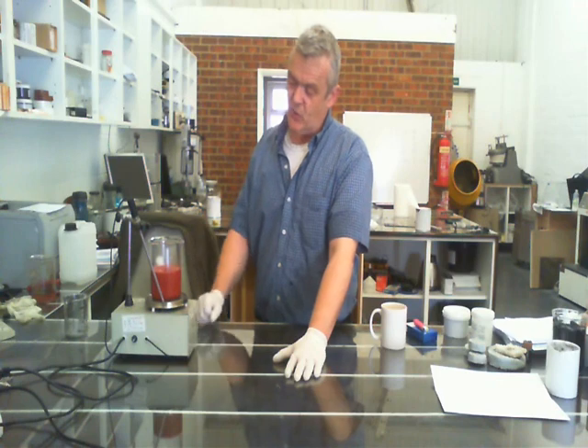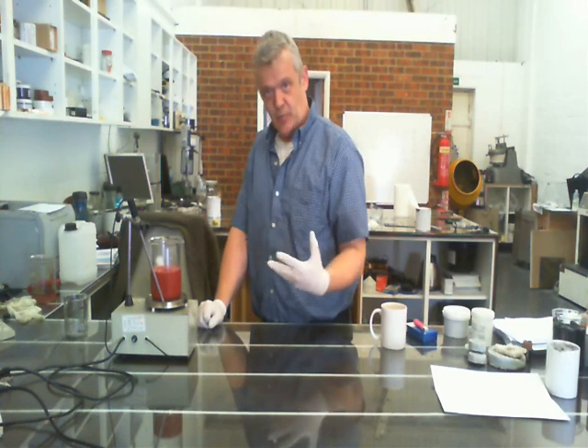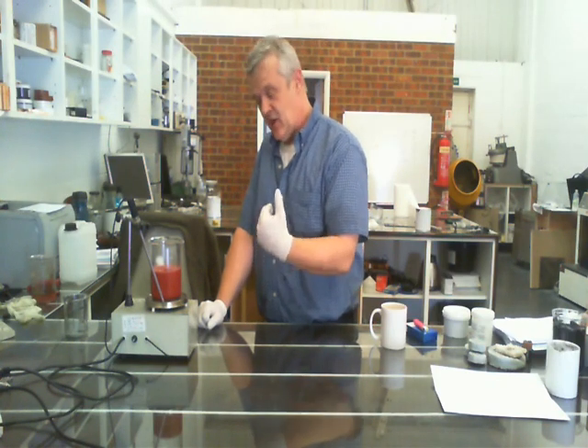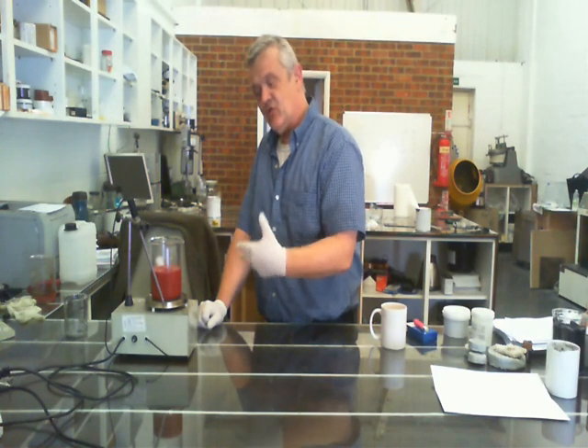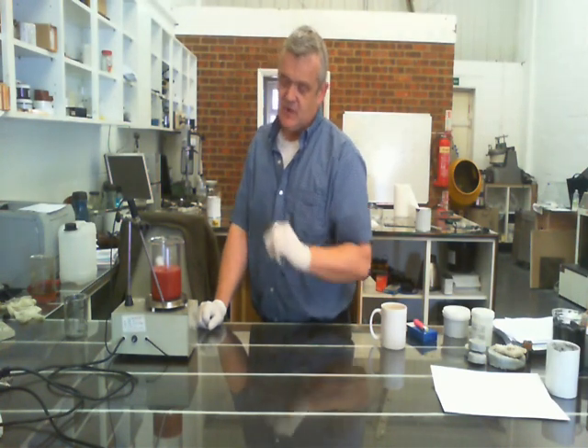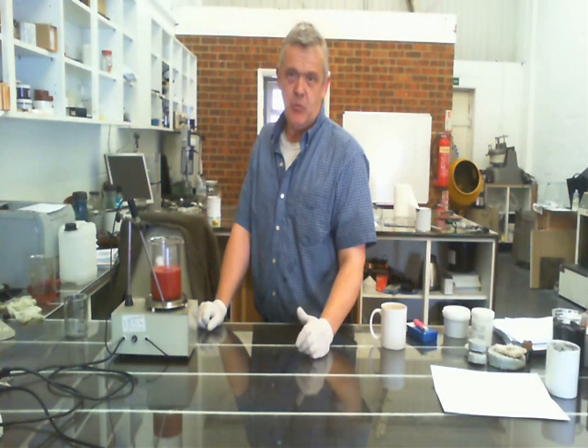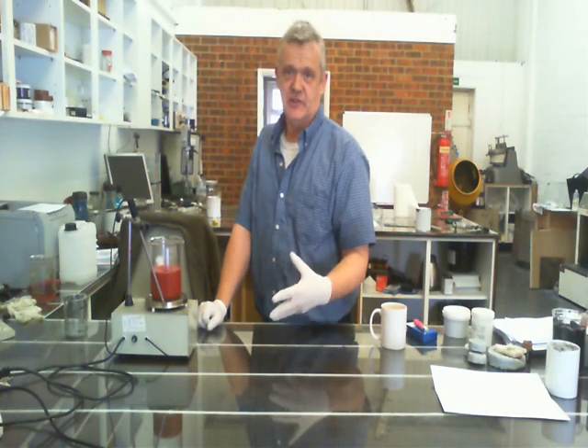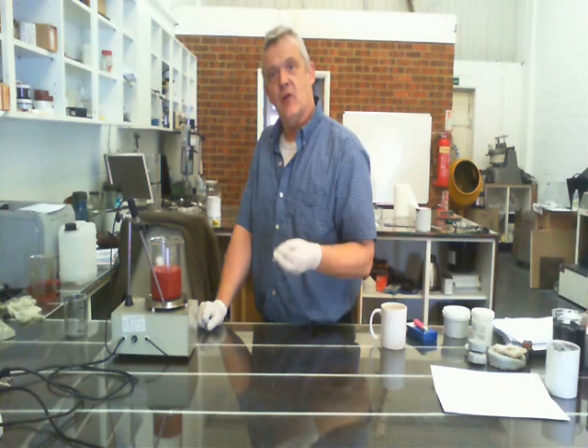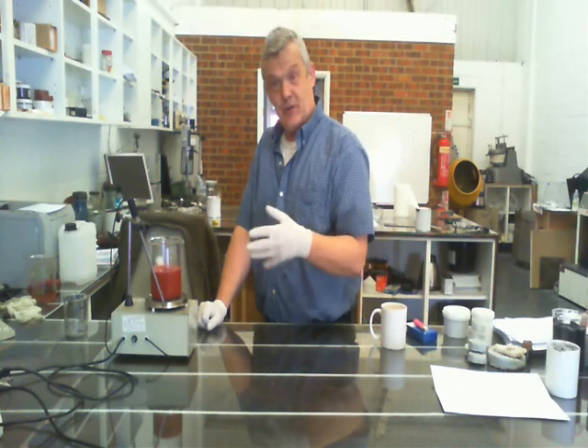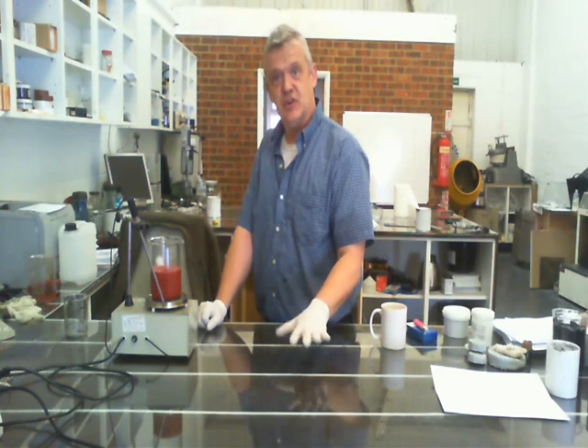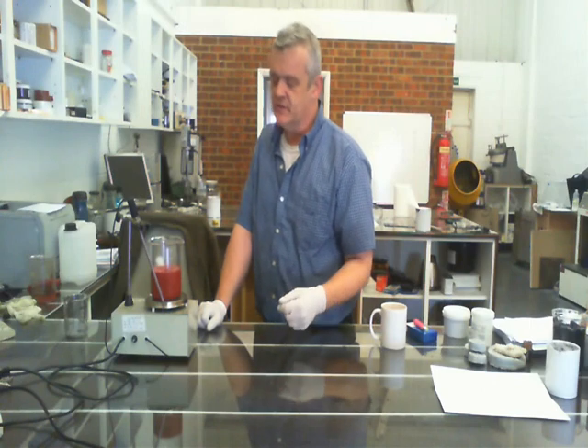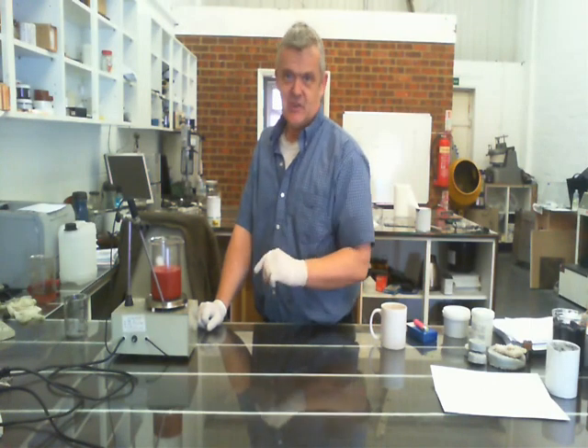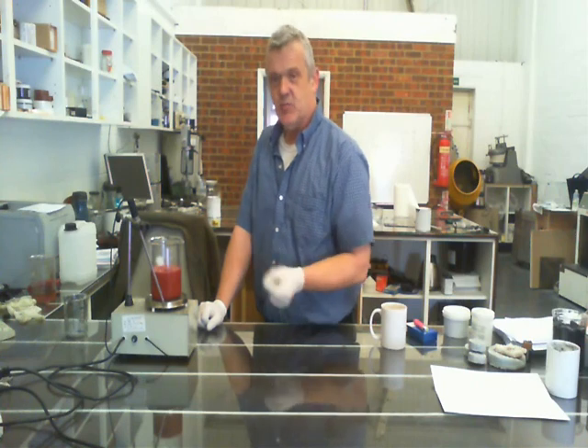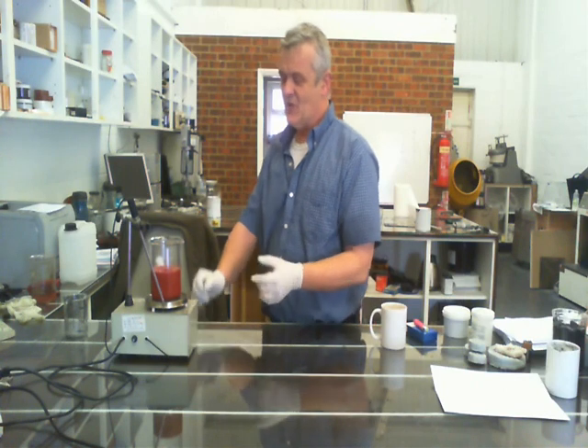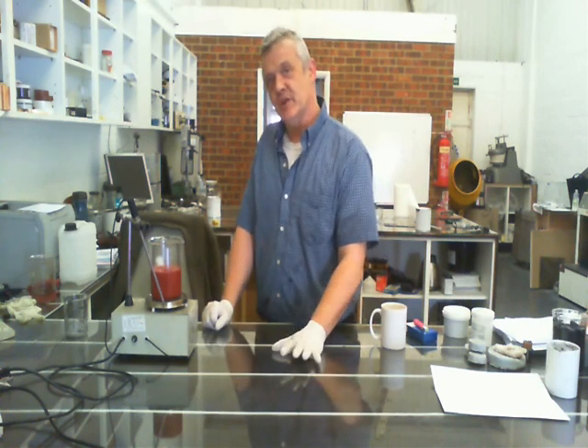Now, I've used formic acid here, and the formic acid attacks the copper oxide, turns it into copper formate, and then the copper formate turns that into particulate copper. The reason I've done that is that copper formate will dissociate under photonic sintering or under heat to give off carbon, hydrogen, oxygen, and copper. The copper will be deposited as pure copper using photonic sintering. It will deposit slightly better if there are copper nanoparticles already in there. So this is meant for a photonic sintering ink.